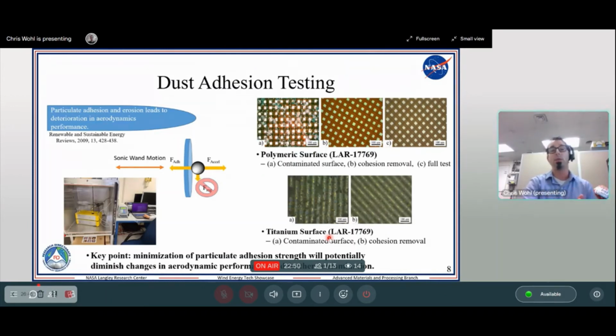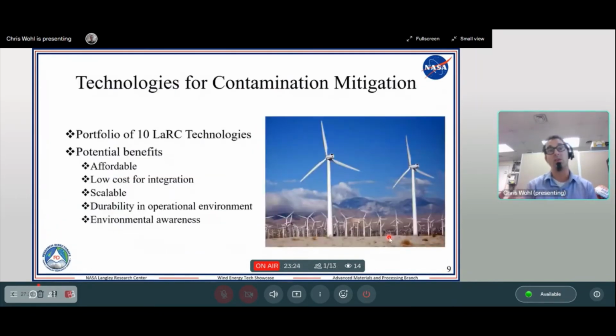Ideally, it would reduce the increase in drag as a result of, say, experiencing a dust storm or something like that. And we've developed this experiment to evaluate these technologies so that we can say, yes, the topographies that we're generating that I'm showing here on the right-hand side for both the polymeric surface and the titanium surface will reduce the adhesive interaction of an incoming dust particle. And again, the idea would be these coatings, these topographical modification approaches would reduce the potential of loss of invested value in that wind turbine and in that wind farm.